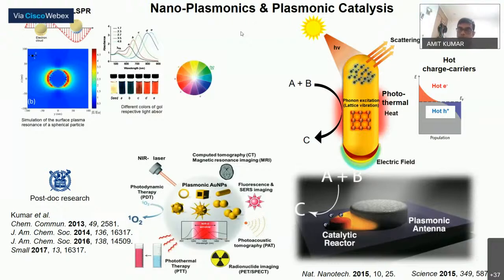One is an increase in the electromagnetic field on the surface of these nanoparticles. Another is that such light interaction can excite hot charge carriers, for example hot electrons and hot holes, which can be utilized for chemical reactions. Actually, what dominates is the lattice of the nanoparticles undergoing vibration, and there is phonon excitation and phonon-electron coupling.